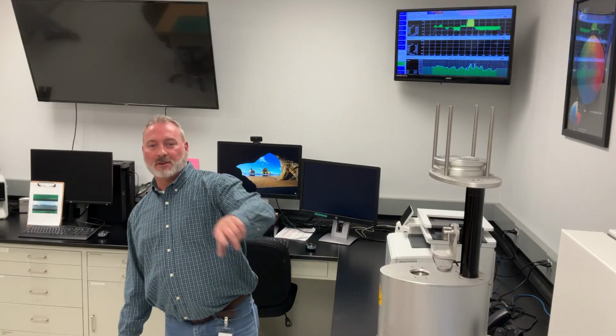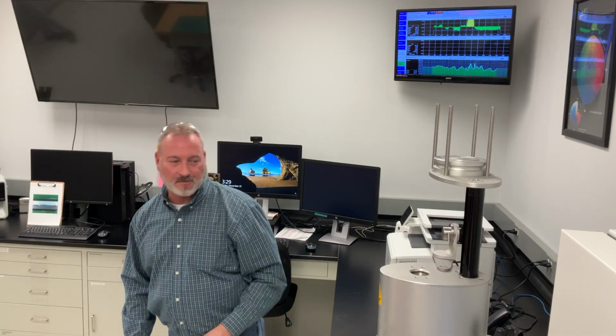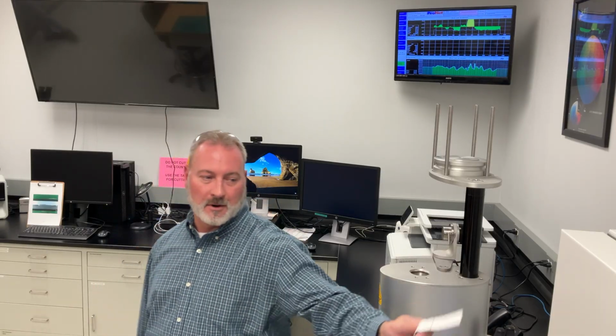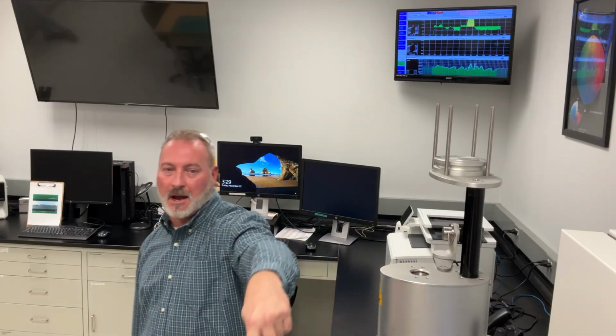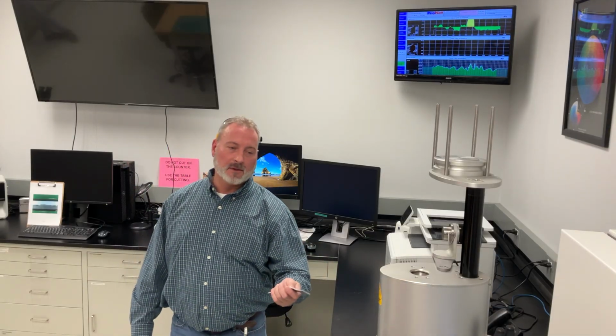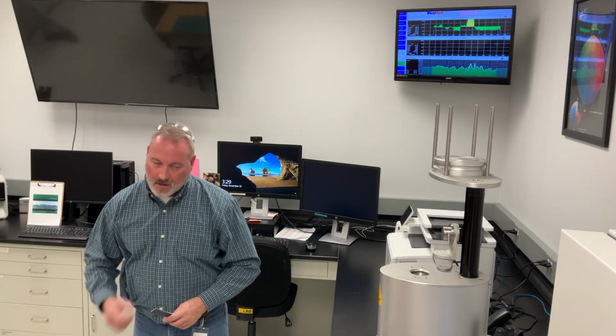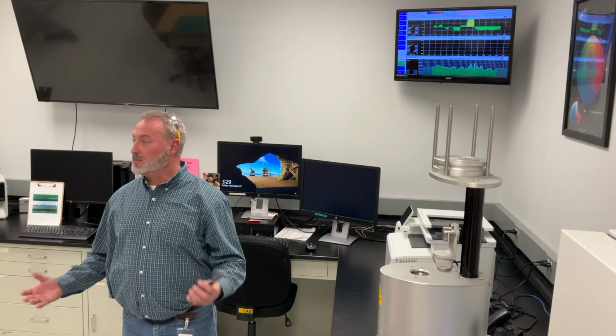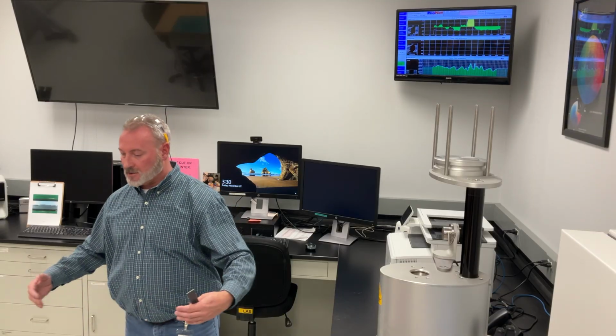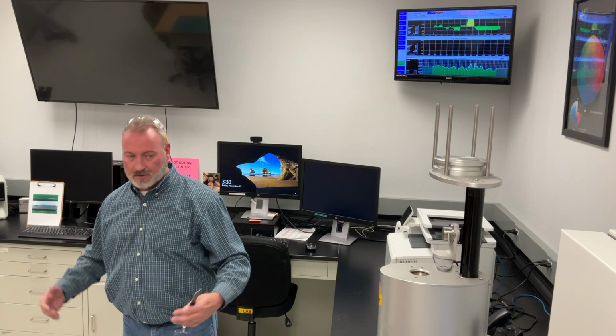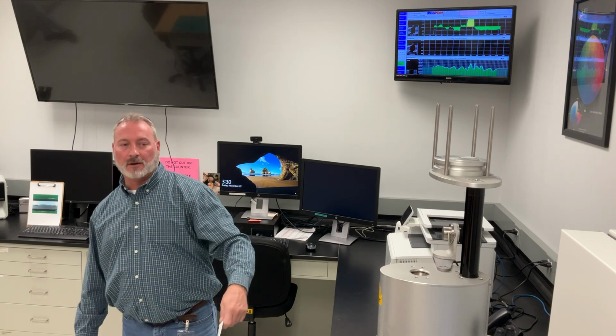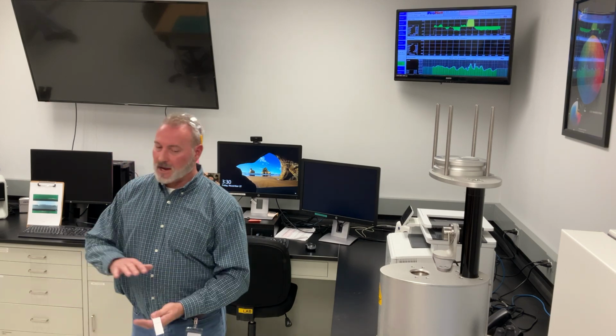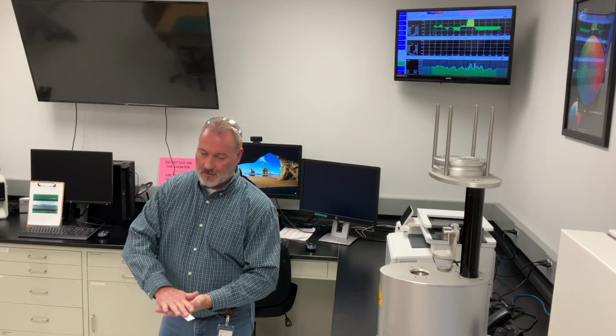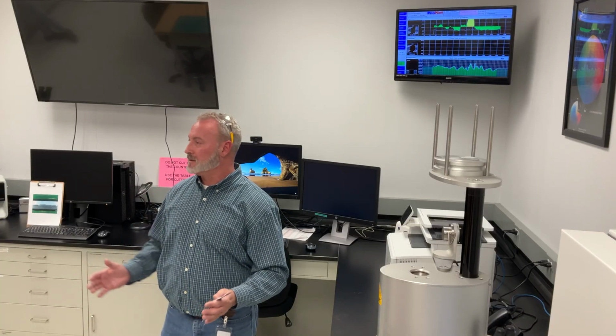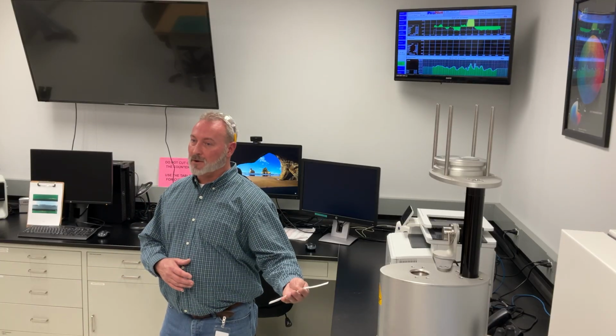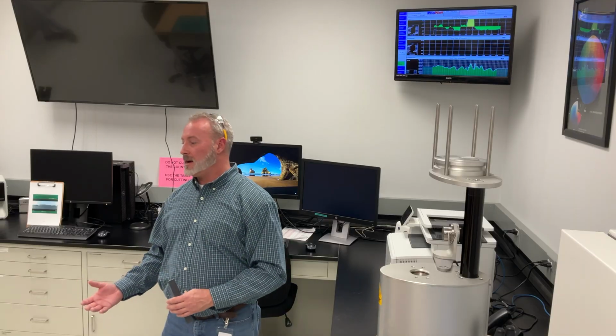I don't know. So these two next things are ovens. This one's set up for your domestic product, that's for BMI, right? And what we do with those ovens here at the plant level is called dimensional stability, right? So they cut out a 12-inch by 12-inch square, put it in the oven for so long, it comes out. We usually have some kind of apparatus that holds that sample flat, then we measure it with a mic, right? So we know it was 12 by 12 going in, and then when it comes out, it cannot grow more